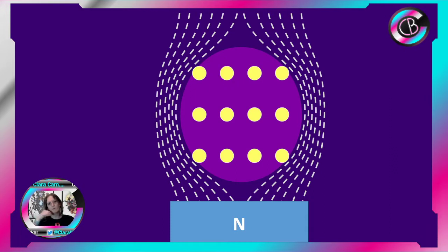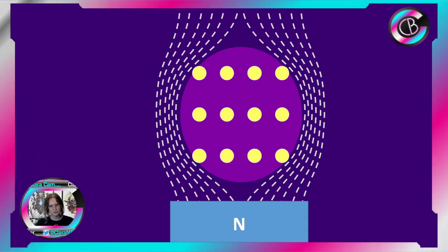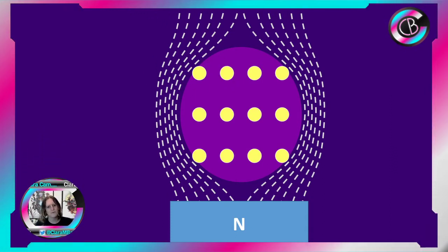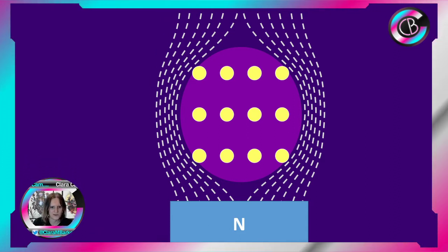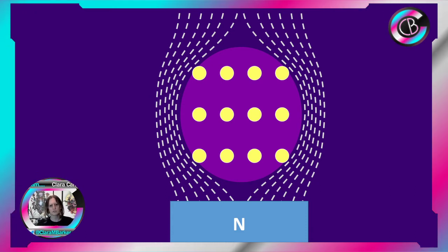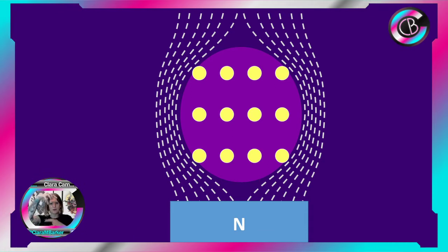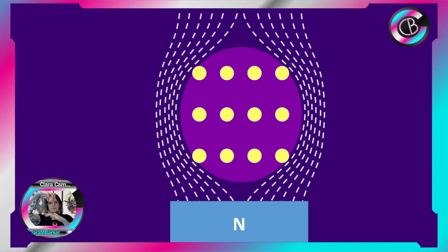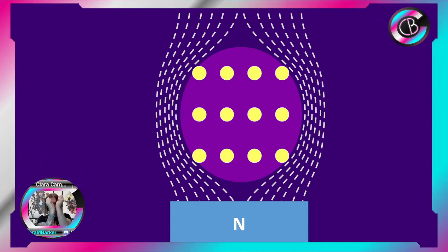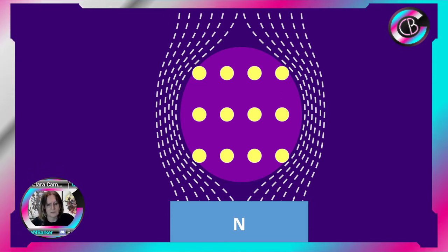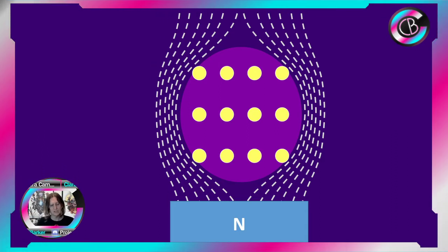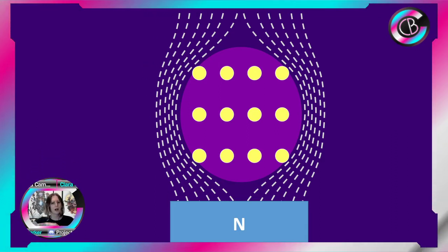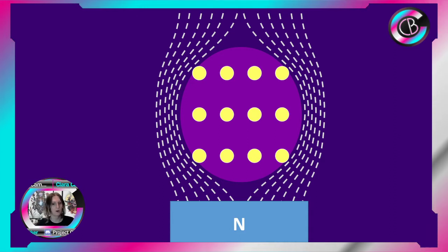But then, when we cool down our superconductor to the critical temperature, what we find with superconductors is that at the same point where all of a sudden they have zero electrical resistance, all of a sudden they expel magnetic fields. So if you have a superconductor and you cool it down and there's a permanent magnet by, the magnetic field is kicked out of the superconductor. It cannot pass through the bulk material. And this is really quite unusual.